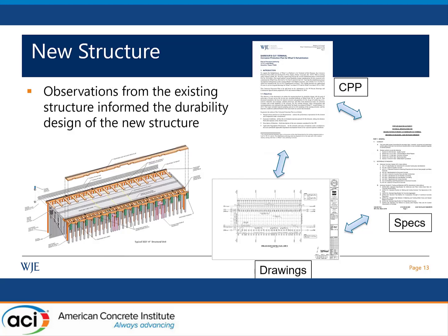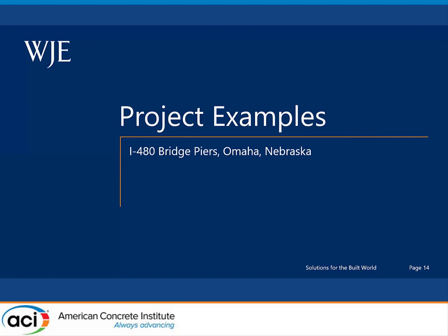And we used all the information we gathered from our investigation at the existing structure to inform the durability design of the new structure. So the correlation was for the surface chloride concentrations, we used that along with what we learned about the propagation time for the different exposure zones to run service life modeling, considering different alternatives for concrete mix parameters, reinforcing material, and concrete cover thickness to achieve 50 years of design service life. And based on that, we recommended concrete mix design parameters that were summarized in a corrosion protection plan or reflected in drawings and specifications. And with that, I'm going to give control to Elizabeth to present our next project example.